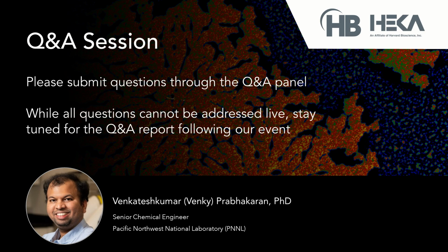That's an excellent question, at least from my side as well, because I used to work with a lot of vacuum instruments, particularly in the ion soft landing technique. I did try it once to use the SECCM in vacuum, but haven't made any measurement. It really depends on the tip diameter, and what I found out is that you need a really small tip diameter and long tapering, so that the microcapillary force at the tip end is enough to counterbalance the vacuum force.